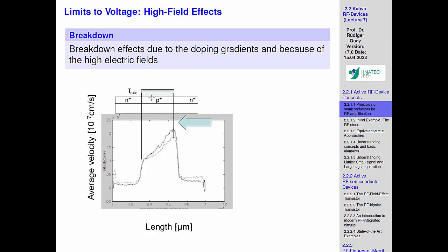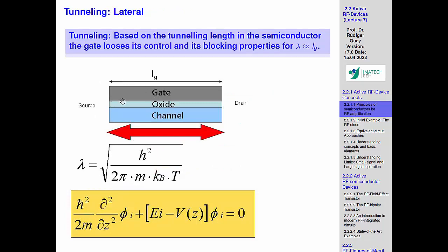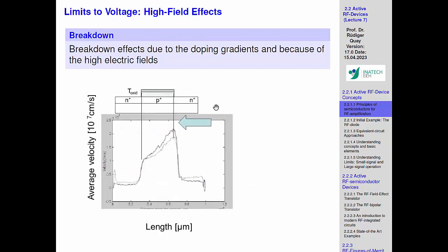And so when you have this idea here for the oxide, you could argue that it's just thin, but it's very balanced. But it's not true, because we accelerate the carriers under the gate, we also hit them locally into very high speeds, or because we're creating doping profiles which cause the field to be relatively focused, you could say. So what we get overall is that there are regions in the transistor, or later on also in the bipolar, which are particularly affected by hot carriers, accelerated nicely. So you see the drift velocity in normal is just maybe 1 × 10⁷, but here they are really turned into high energy states. Yeah? And that's what really limits devices when they're getting small.